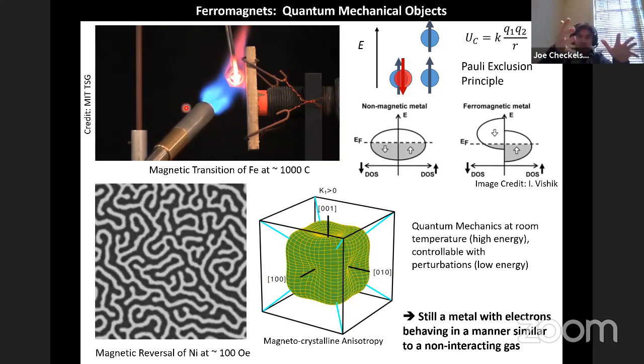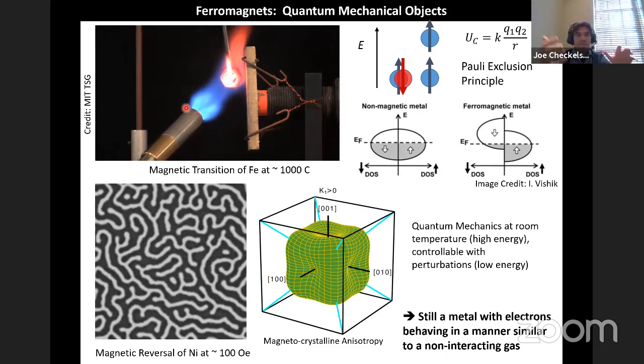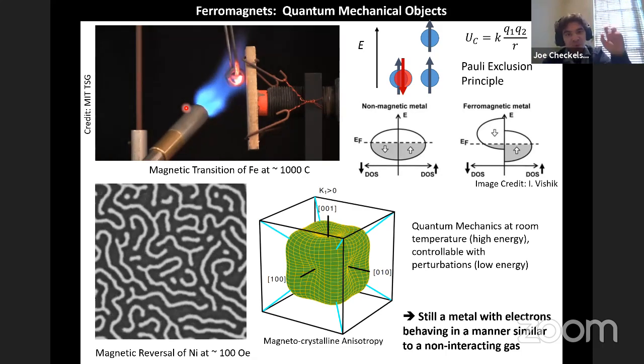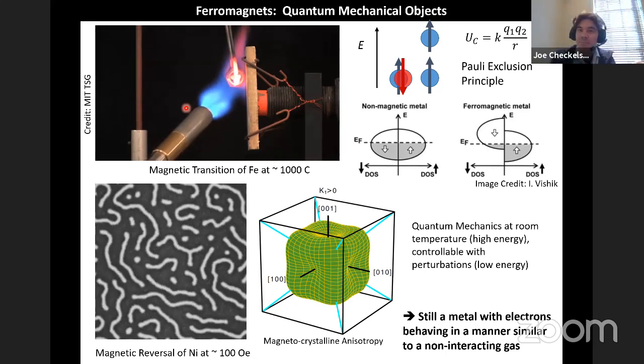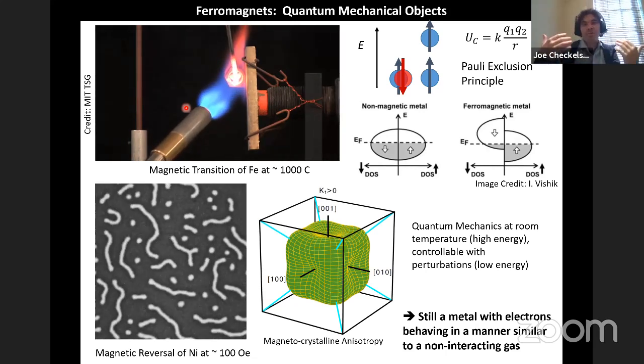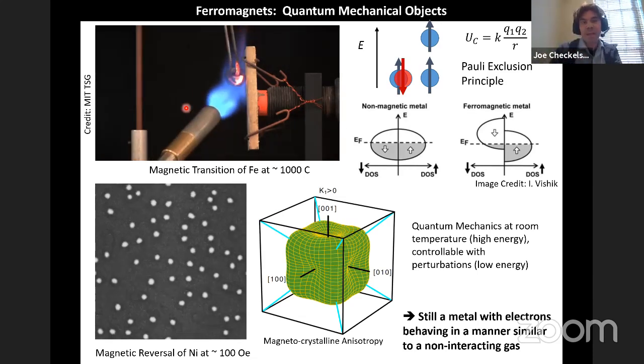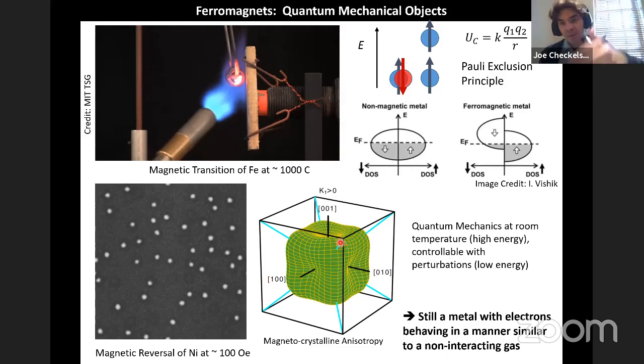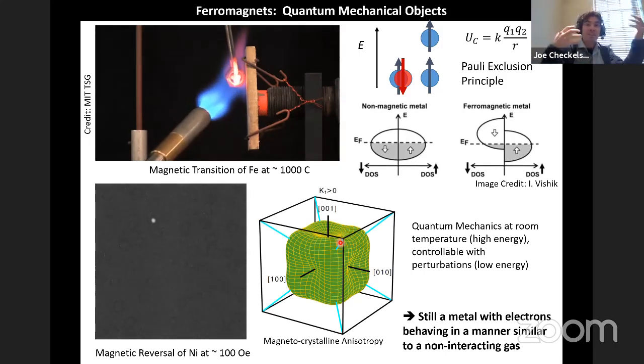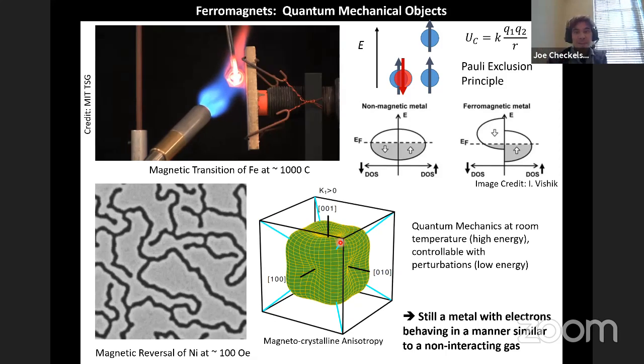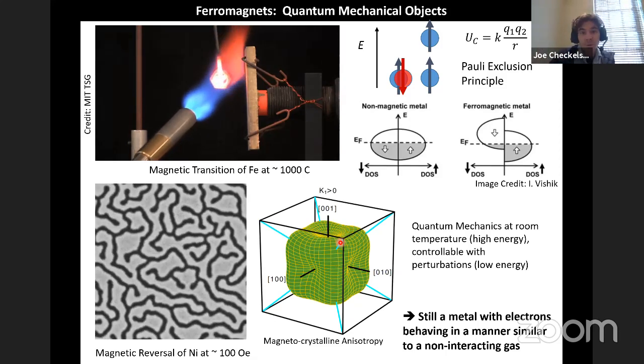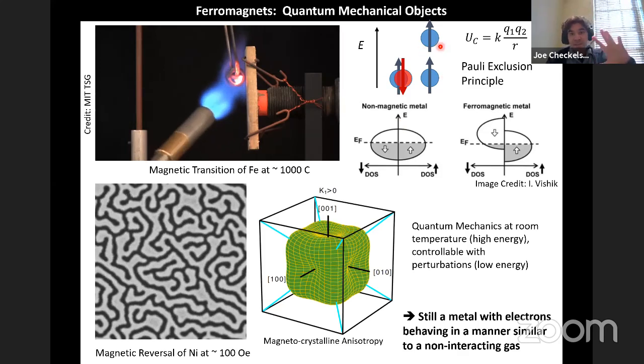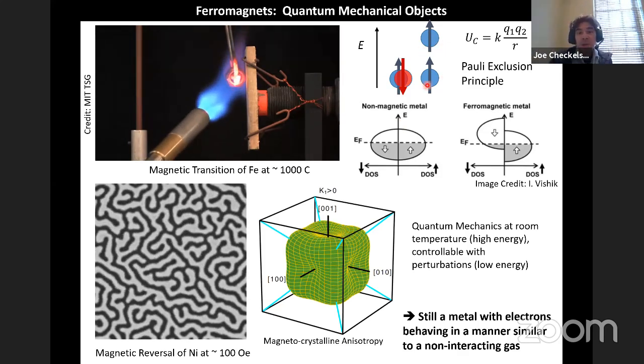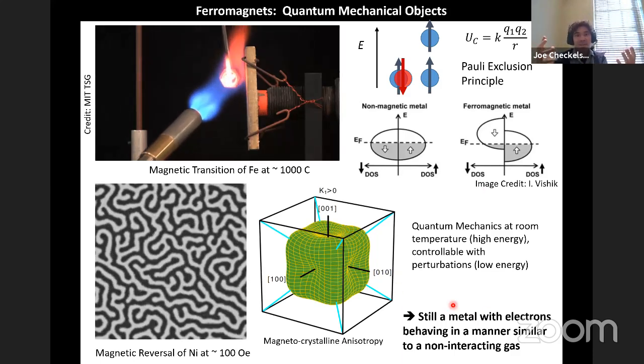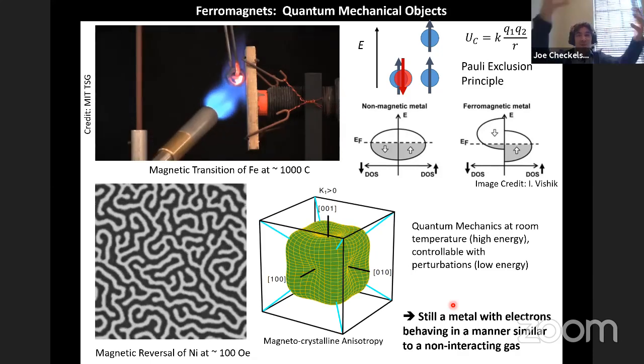And the key point about this, and this ferromagnetism more generally, is that when you're reversing nickel, you're not destroying the magnetic phase, you're just reorienting the magnetic moment. And it is that basically a different physical energy scale controls the orientation of a magnetic moment, whether it's a local crystal electric field or spin orbit coupling. It allows you to take this robust quantum mechanical thing and move it around if you want. And then at the same time, something else that's also important is that despite the fact that you have all of this exotica happening with the spin degree of freedom, by and large, simple ferromagnetic metals still behave like metals, almost like some non-interacting gas of electrons. And so you can actually still think about metal physics even with all this that's going on underneath.